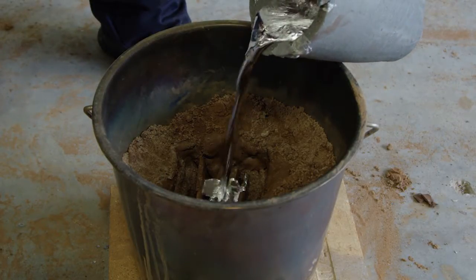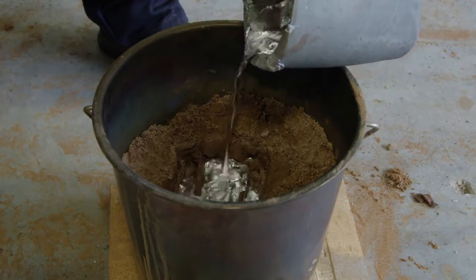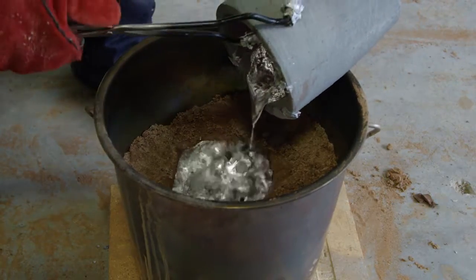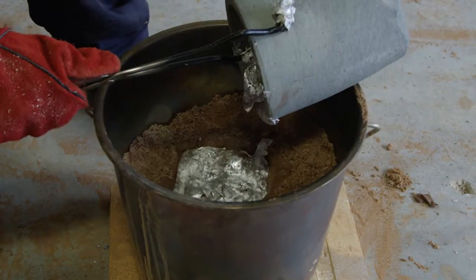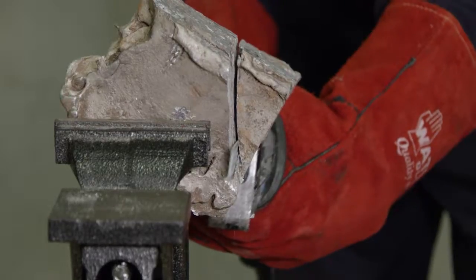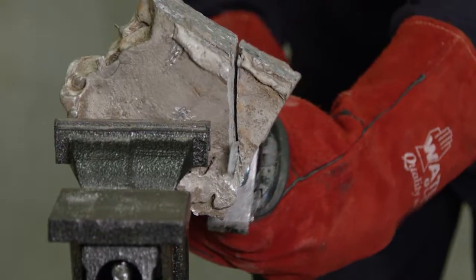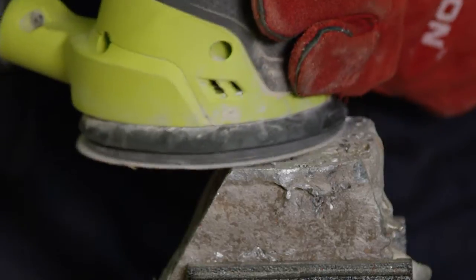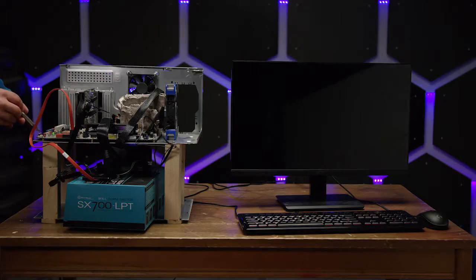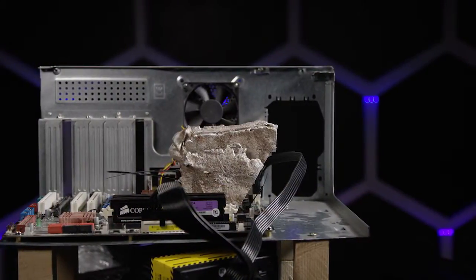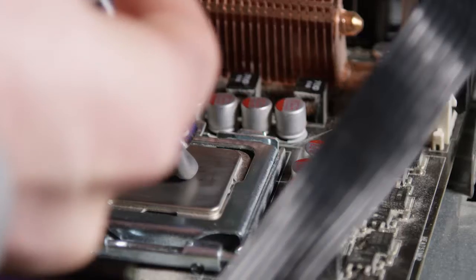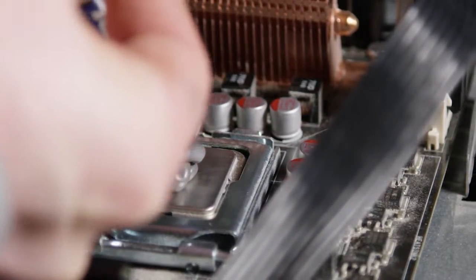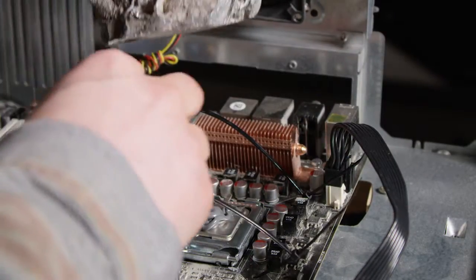Upon pouring the aluminum into the mold, it started bubbling from the steam escaping from the clay, making the metal of the finished product more porous, a problem we hadn't had before when we were using green sand. So then, with a bit of massaging from the reciprocating saw to make it fit on a motherboard, it was finally ready to mount. The processor chosen was an Intel Q6600, mainly because the old Asus motherboard it was on was the only one where the heatsink didn't interfere with the VRM, and to help fill in the air pockets on the bottom of the heatsink, we added a more than generous dollop of thermal paste, topping off the creation with a handful of zip ties.